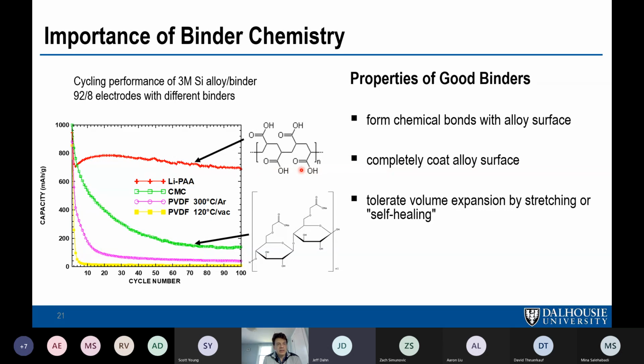Okay, that's incredible. The way you test that out, it's not easy to do, because electrochemists have measured the electrochemistry of polyimide for a long time, and they did that by spin coating to get a thin film. These binders are about 14 to 20 angstroms average thickness on the particles. If they're too thick, then your diffusion is bad. If they're too thin, you get holes. So a good target is 15 to 20 angstroms thick.